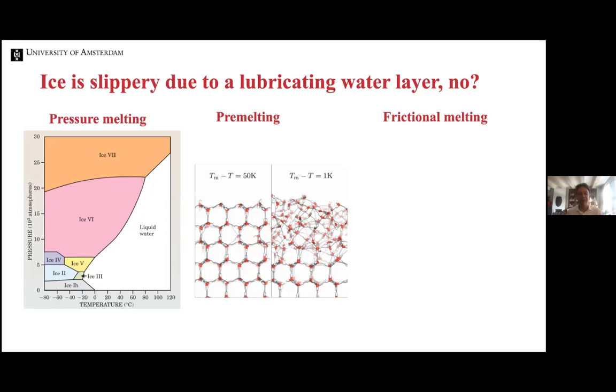There's still people who believe that because the liquidus, or the liquid-solid phase transition in the pressure-temperature diagram, has the wrong slope, it actually means that you can melt ice by exerting pressure on it. And so if your skate exerts a large enough pressure, it will in fact melt the ice. There's two problems with that. The one is that the pressure exerted by a skate is actually not high enough to melt ice. And the second, and perhaps even more important problem, is that below minus 22 degrees C, the phase diagram of liquid water and ice actually tells you that you can no longer melt the ice.